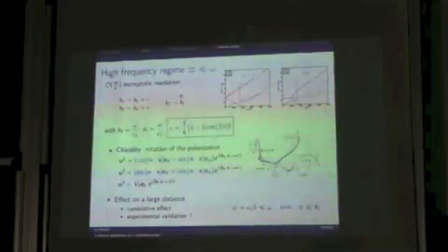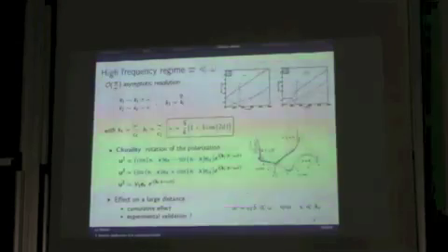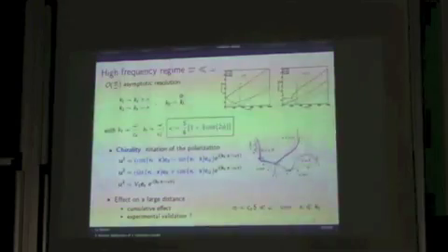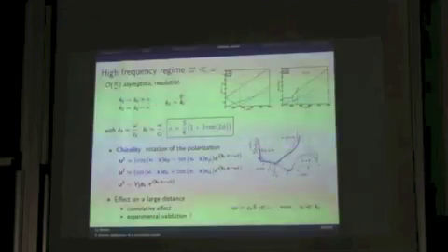But when this propagates on a long distance, you have a chirality aspect. That means that the polarization changes slowly during the propagation. Maybe this is due to a cumulative effect of the density of the defect. And what is sure, it's not related to the curvature, it's related to the other linear part of the torsion.